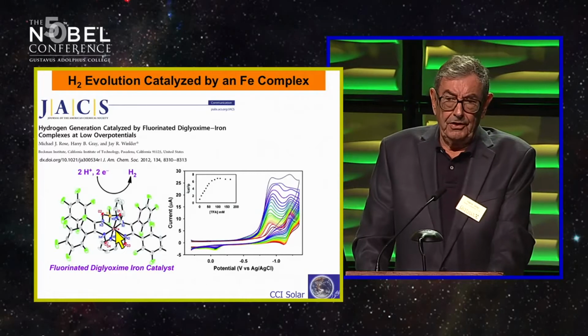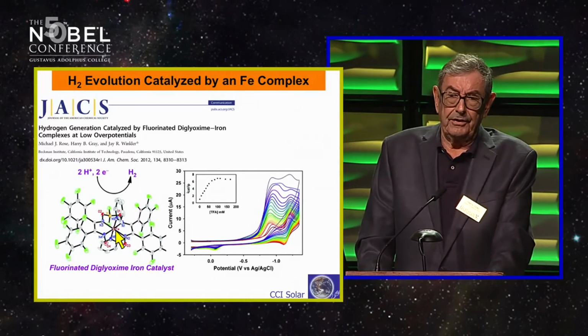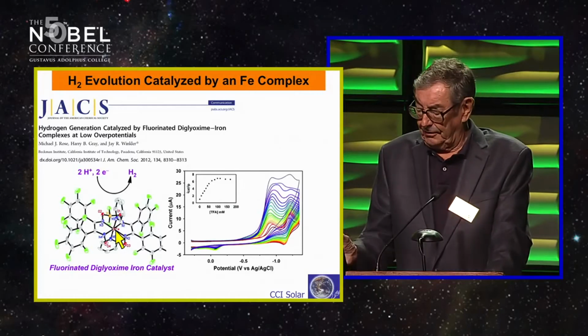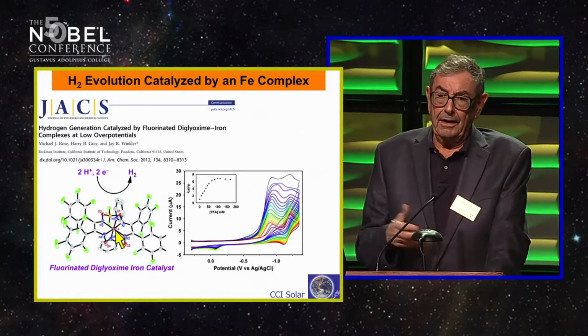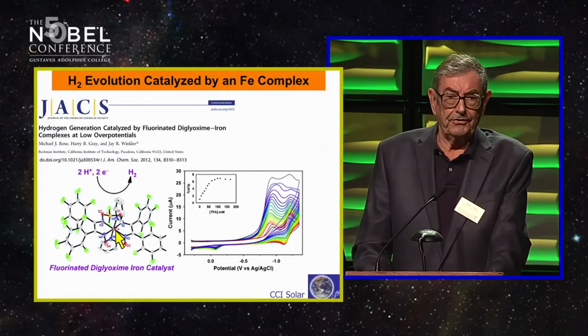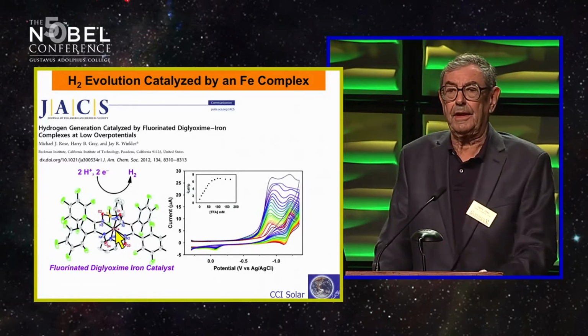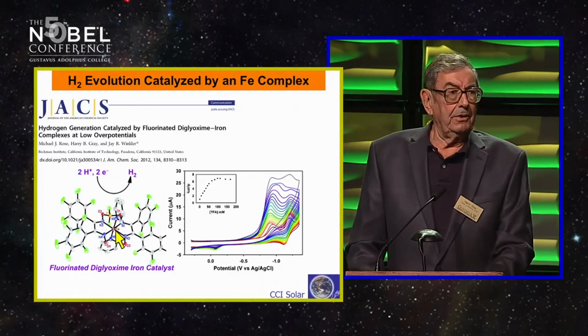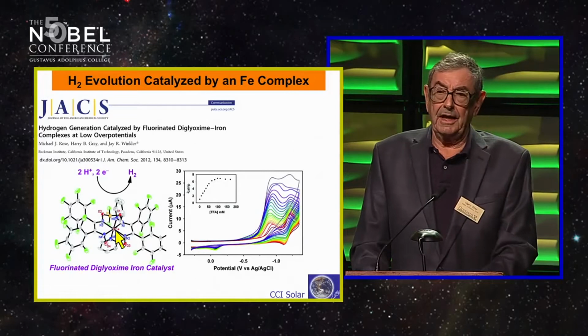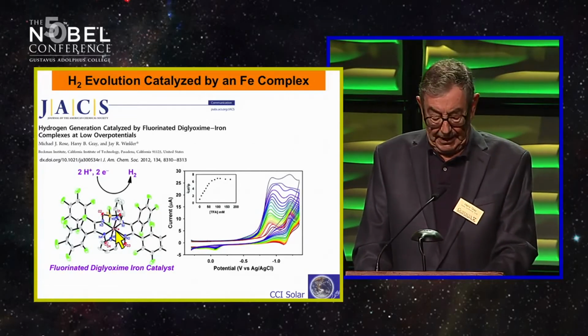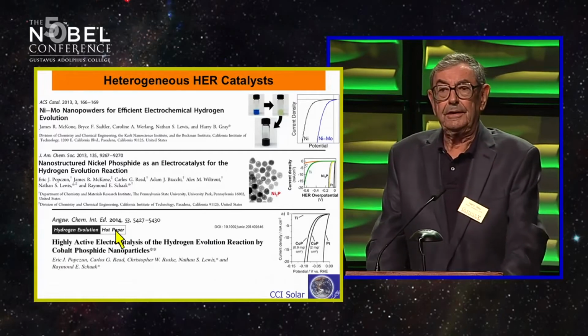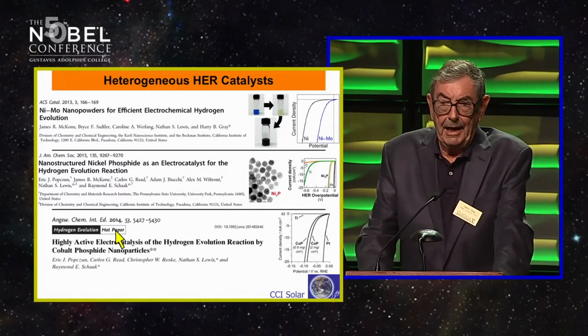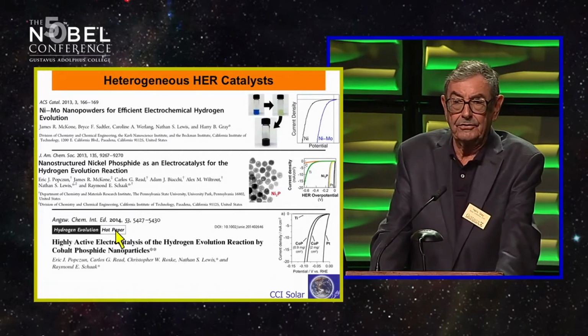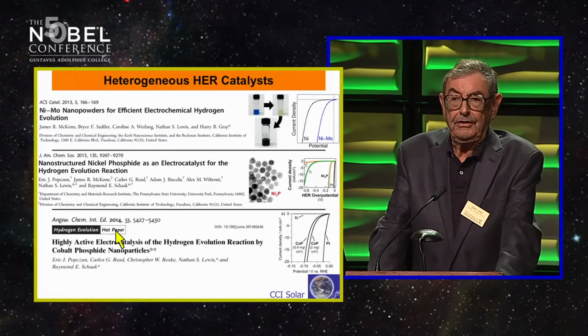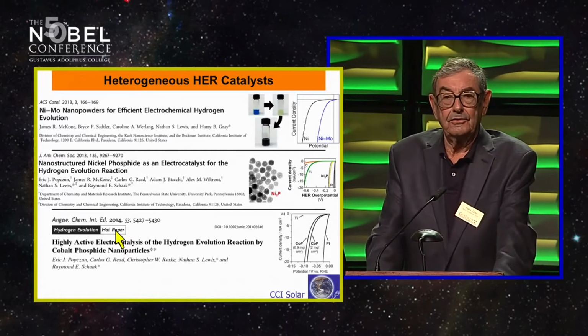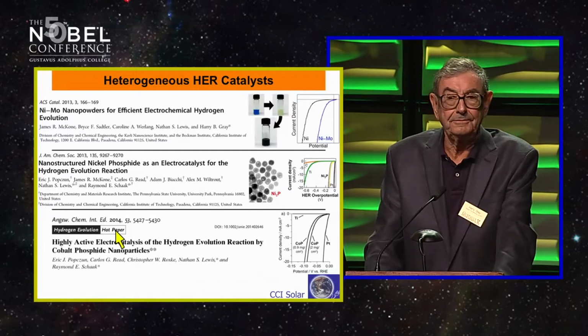But as good as these homogeneous catalysts are now, and they're very, very good, it's likely in the long run they won't last because they contain organic components. And our devices have to be robust. They have to work for hours and hours and hours without degradation. So it's likely that we'll have to use solid-state materials not only as the semiconductors, but also as the catalyst. And so we have engaged in the last few years in a campaign to make new solid-state catalysts to evolve hydrogen. And the good news is we've got 3 solid-state cheap materials that are as good as platinum in evolving hydrogen.